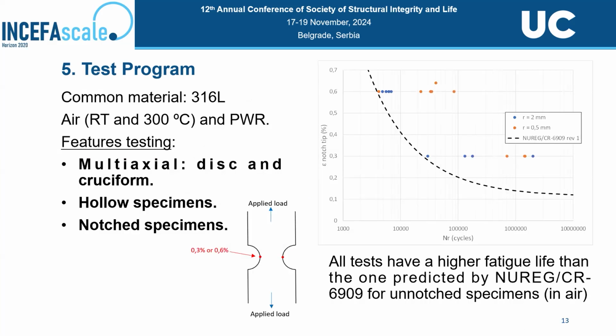But we are performing another specific test that could be used for the industry and for studies: a component scale test. And in the same condition, we are studying this geometry that, in multiaxial, is inclusive from a specimen, a hollow specimen, and not this quite common in components. So we have to look for this definition of strain at the notch tip, and we are applying this strain in the environment. So up to the moment, all tests that we perform have a higher fatigue life. And okay, now we are reviewing this strain measure in case we have made any error.